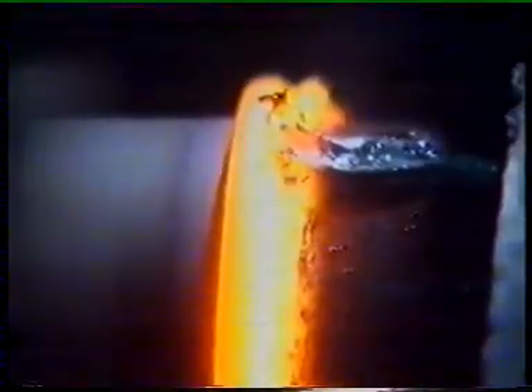As the two abutting faces rub together, friction produces heat, and localized hot plastic zones are produced. With the end load maintained, heat continues to be generated until the whole interface has reached a uniform temperature. At the same time, the plastic starts to flow outwards towards the periphery, carrying with it any oxide present at the joint face. When sufficient heat has been generated, the rotation is stopped and the end load may be increased.